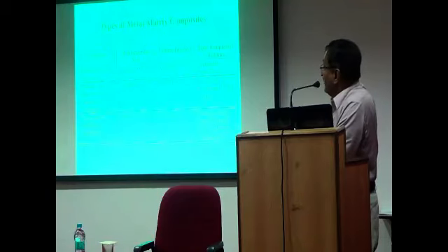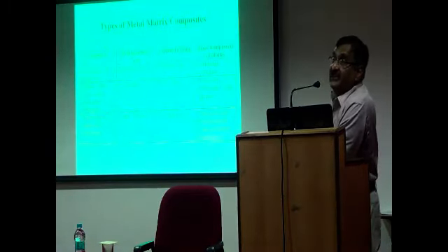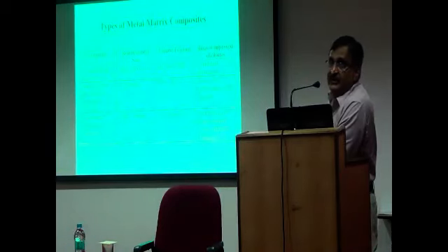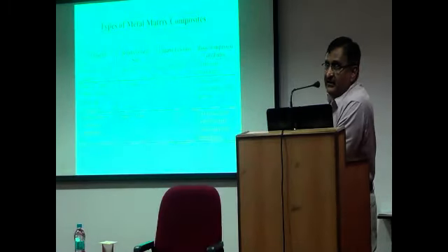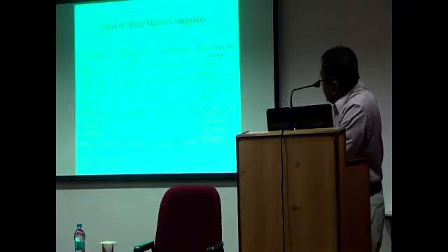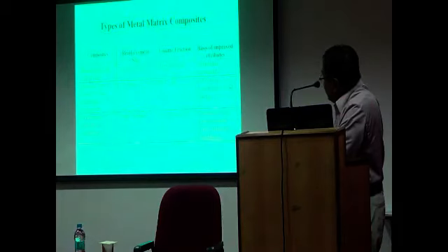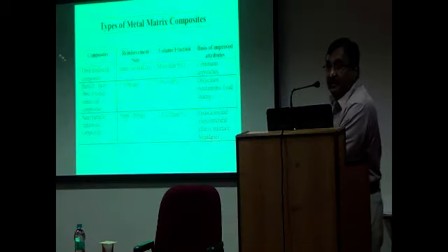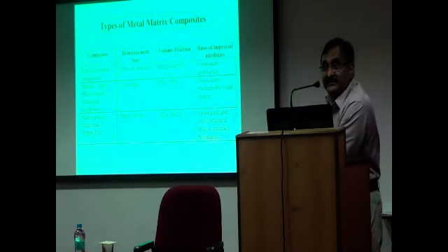When the people gave it up, because of the cost and manufacturing difficulties associated with fibers, people started looking at particles, short fiber or whisker as an alternative reinforcement. The particles, I mentioned to you, are anywhere between 50 to 100 micron size. It's just a powder. And if you look at the volume fraction, it's about 10 to 30%. It means that compared with the long dimensions and higher volume fraction, you decrease the size and decrease the volume fraction in order to achieve the same level of improvement in the properties. Okay.